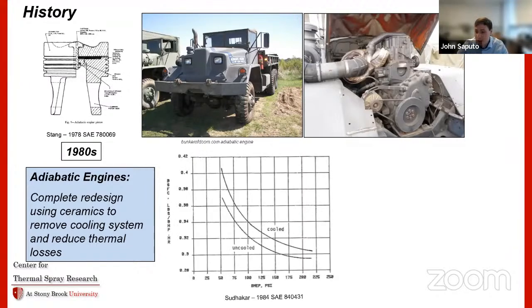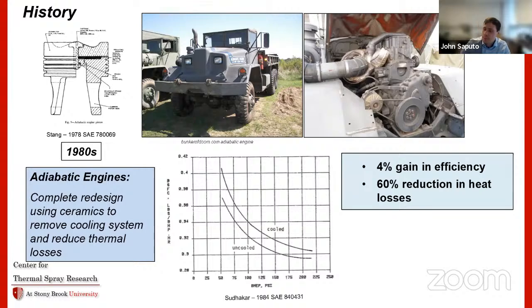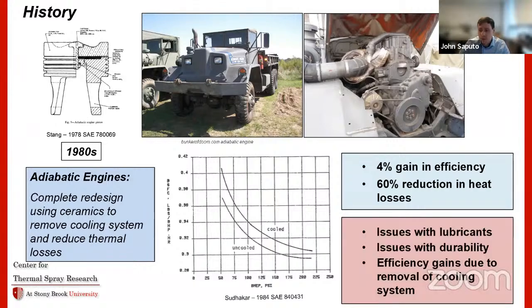and did platform level performance testing. This is another example looking at fuel consumption versus load on the engine. You can see at every point they test that the uncooled engine is more efficient than the cooled engine, which isn't really a great surprise. But they only saw about a 4% gain in efficiency and a 60% reduction in heat transfer losses, which is kind of interesting. The majority of those performance benefits actually come from removing the cooling system. So you're removing this parasitic loss that normally gets taken away from the engine, and not necessarily gaining performance benefits from directly having the ceramic components.